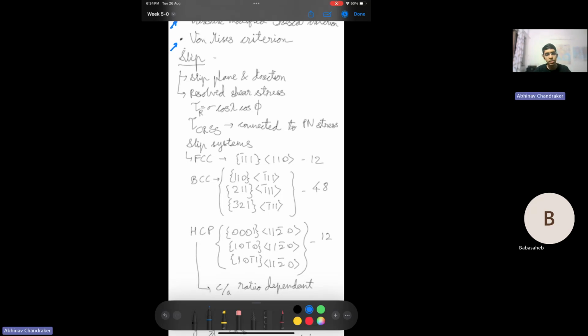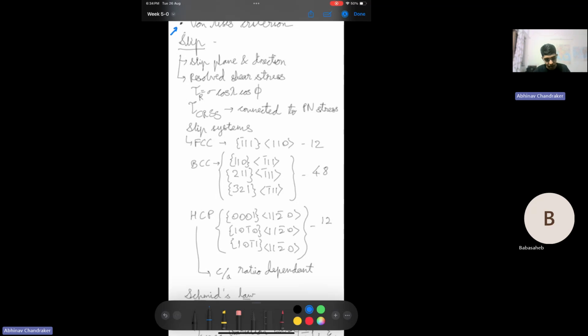All the fundamentals of dislocations which we looked at till now will now come into use, because this is connected to dislocations only. Slip basically refers to glide of a dislocation on any particular plane in any direction. That plane and direction are called slip plane and slip direction. Because the dislocation is gliding, there is an atomic bond switching happening, and that can be seen as a small slip occurring. Once the dislocation moves across the whole material and reaches the surface, it comes out from the surface, and that causes a step, which is also called a slip. That's why we say that slipping occurs due to movement of dislocation.